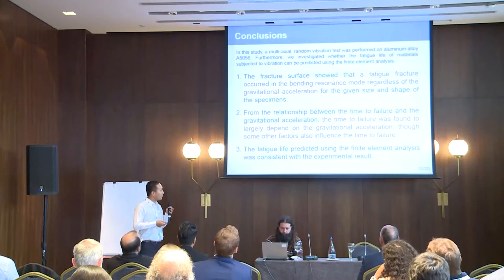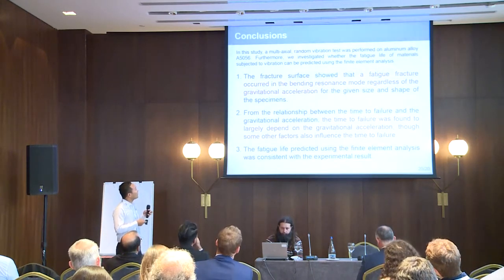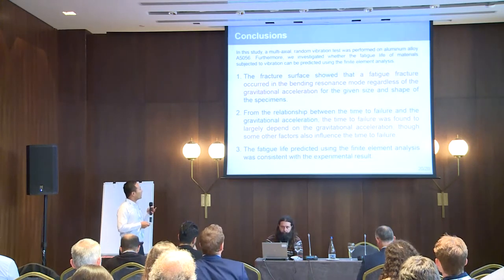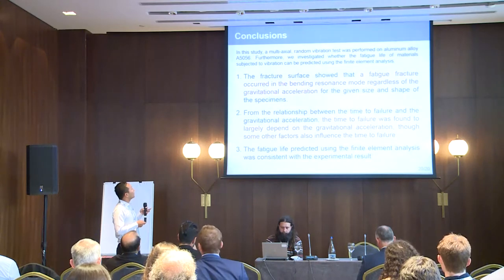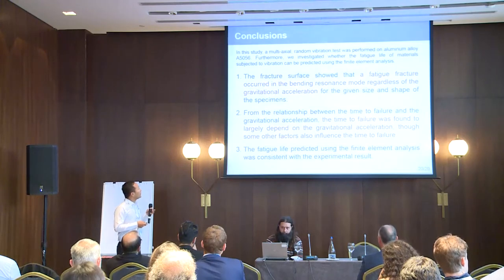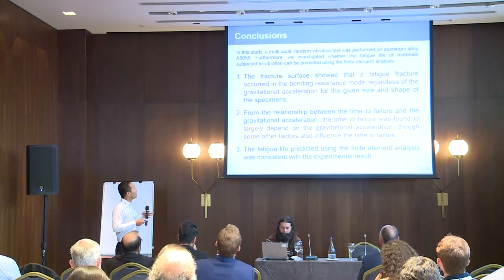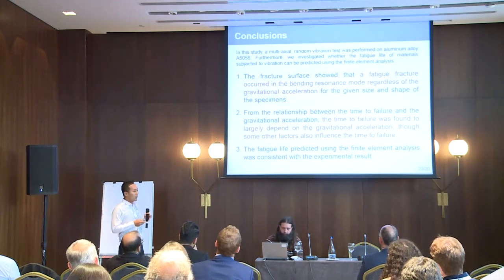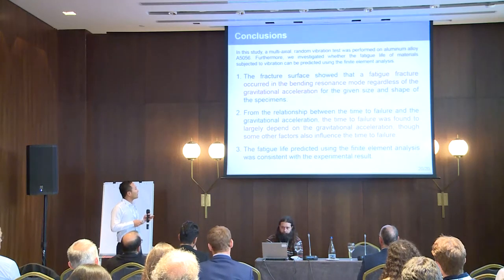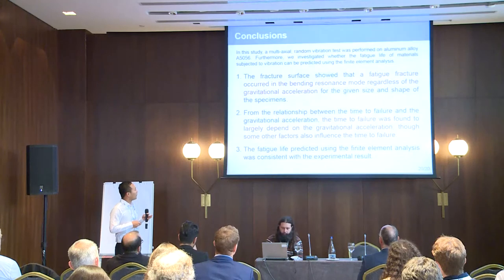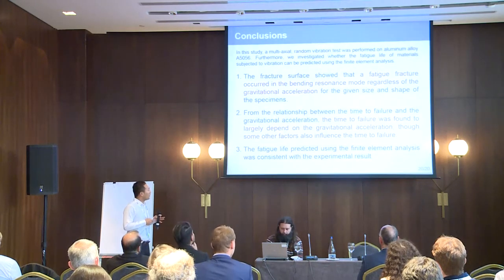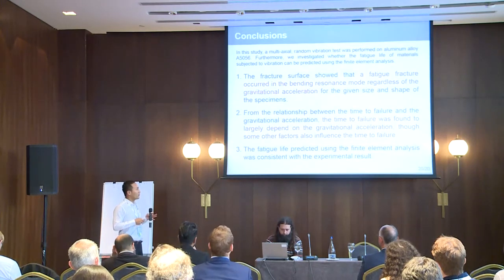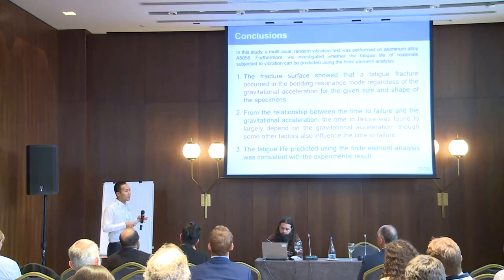In conclusion, a multi-axial random vibration test was performed on aluminum alloy A5056, and we investigated whether the fatigue life can be predicted using finite element analysis. First, the fracture surface shows that fatigue fracture occurred in the bending resonant mode regardless of the gravitational acceleration or specimen size and shape. Second, the time to failure was found to largely depend on gravitational acceleration, though other factors also influenced it. Third, the fatigue life predicted using finite element analysis was consistent with the experimental results, and we plan to investigate this further.